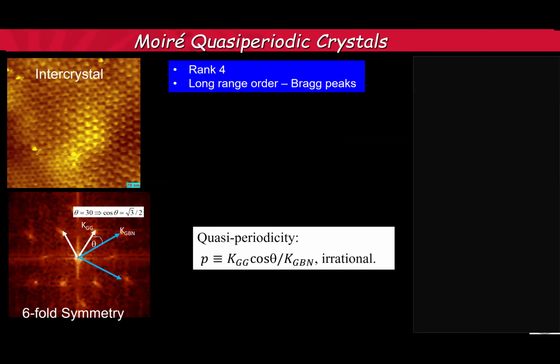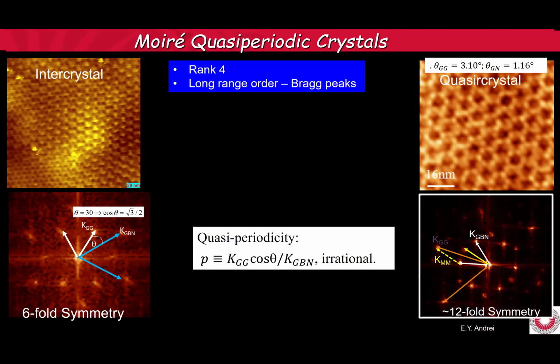So we calculate how far you have to go before you see something periodic. If it's like 10 times larger than your sample, you say, okay. And this is our quasicrystal. We have one. We have 12 points here, but they're not quite a quasicrystal because you see, these are our six peaks, and in between we have, I don't know if you can see them, the other peaks at 30 degrees that come from Moiré of Moiré. It's a superposition of the KGBN and KGG, and that gives you another K vector that's exactly at 30 degrees, with kind of the same length. So you get something that looks like a 12-fold symmetry, but it's not quite. But that's as good as we can get without going to 30 degrees.